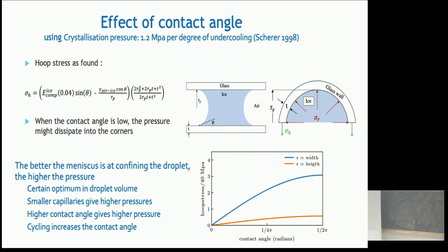But it tells us that it's really a very complicated problem, crystallization in porous media, because we have an optimum in droplet volume. If the pore only has a droplet in it, the droplet will not grow sufficiently to reach the other side, and so that will not cause any pressure. If there's too much, it will simply grow out of the pore. And so what is essential is that surface tension actually confines the liquid to the pore.